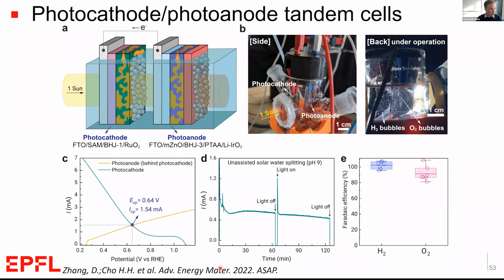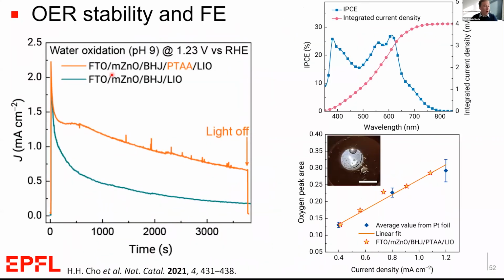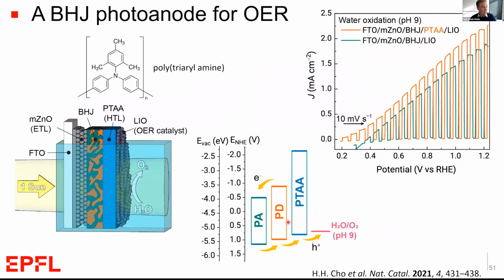And you can check out the paper that was published recently. But this is an important point. One thing that we always have to think about in the OPV field is, are the materials that we're using stable under the conditions that we have for testing? In this case, under pH 9, which is better for the OER, but more challenging for the hydrogen evolution reaction.